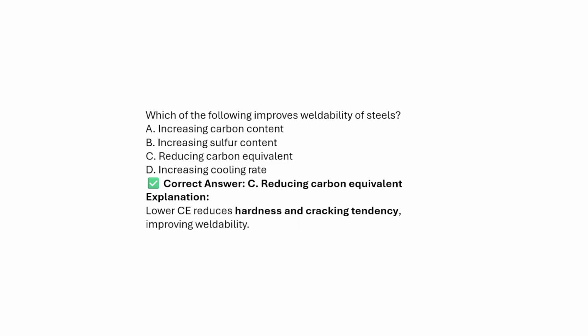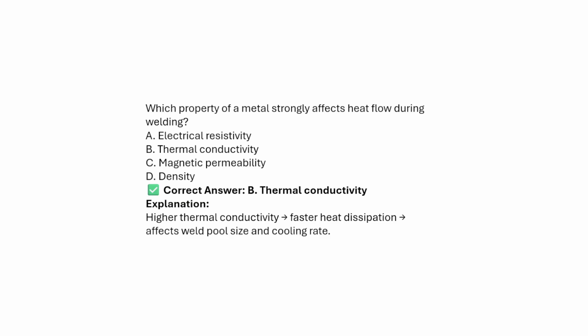So next, which of the following improves the weldability of the steel? Which factor will improve the weldability in the steel? Option A, increasing the carbon content. Option B, increasing the sulfur content. Option C, reducing the carbon equivalent. Option D, increasing the cooling rate. The answer will be reducing the carbon equivalent. If you reduce the carbon equivalent, there is less formation of martensitic phase and less martensitic tendency, so less susceptibility to crack propagation. So option C, reducing the carbon equivalent. Lower carbon equivalent reduces the hardness, that reduces the crack tendency, that improves the weldability.